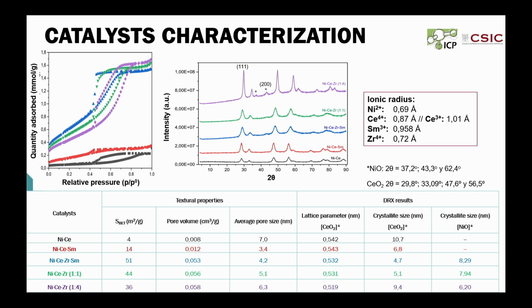On the other hand, the XRD results show reflections of cerium oxide with a fluorite-type structure, with no separation into other phases except for nickel oxide in some cases. The change that we can see in the lattice parameter is due to the difference in the ionic radius of samarium and zirconium when they are incorporated into the lattice of ceria, forming the mixed oxide.